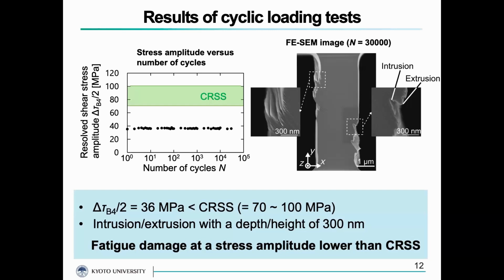However, as we expected, intrusions and extrusions with a depth and height of 300 nanometers were formed. Similar to copper single crystal, micro-sized nickel single crystal also fatigues at stress amplitude lower than CRSS. To reveal the underlying mechanism, we conducted another 4 cyclic loading tests with fewer cycles and observed the interior.